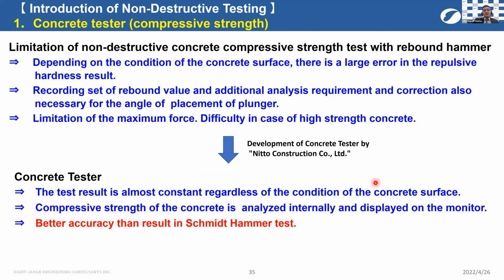The current slide is about the comparison of strength test using rebound hammer and concrete tester. As we all know, the surface where compressive strength test using rebound hammer is conducted should be smooth and dry. So depending on the condition of concrete surface, there may be a large error in repulsive hardness. Whereas the test result using concrete tester is almost constant regardless of the condition of the concrete surface.